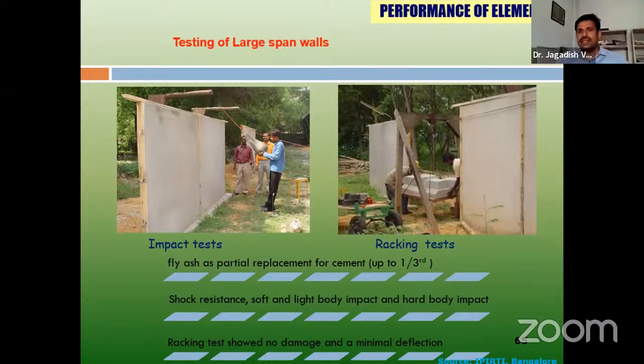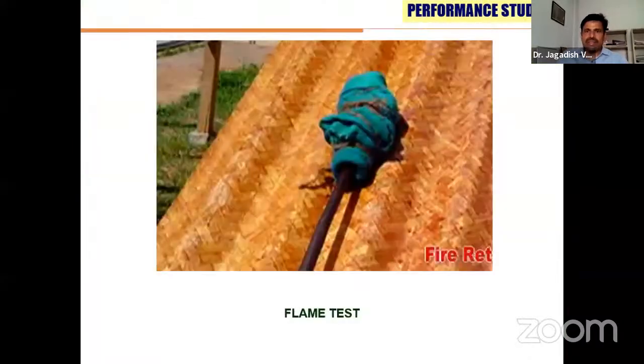Particularly the cement mortar, whatever we've used is 1:3. A part of the cement can be replaced using any of the cementitious materials like fly ash or GGBS. So one third of the cement has been replaced using GGBS and fly ash. And when we conducted the tests on the wall, like shock resistance, soft and light body, hard body impact, and racking test, there was no damage observed, with a minimum amount of deflection, particularly for the racking test.